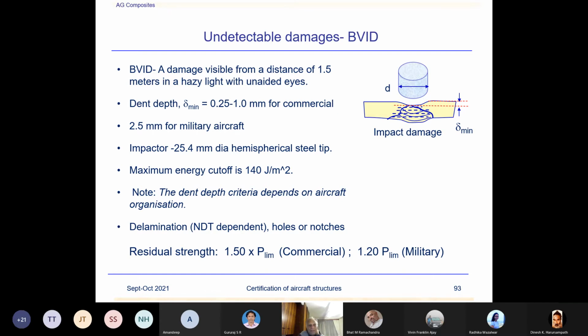Then depth. Now, depending upon the organization, the depth could be 0.25 millimeter to 1.0 millimeter for commercial aircraft. This is after the damage relaxation. You try to impact it. Suppose at the time of impact, the damage is 0.3 millimeters, 0.4 millimeter. After 24 hours, that 0.4 millimeter may drop to 0.25 millimeter because it relaxes. Composites are viscoelastic materials, and with time they relax. So what happens? The initial damage, the dent depth would reduce after 24 hours or after 2 days.